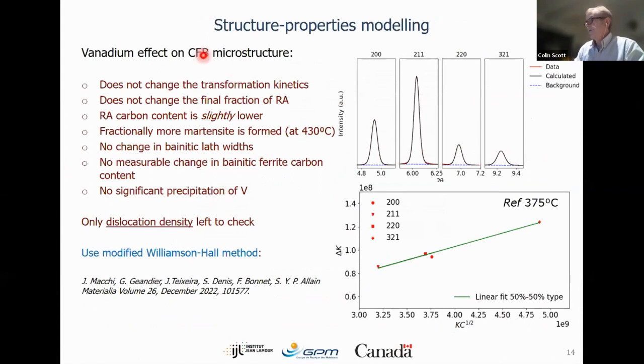So, okay, why does vanadium make these steels stronger? Well, we know it doesn't change the transformation kinetics. It doesn't change the final fraction of retained austenite. There's a slight difference in the retained austenite final carbon content, a fractional difference in the amount of martensite that's formed at higher temperatures, but not really at lower temperatures. No change in the bainite lath widths, no measurable change in bainitic ferrite carbon content, and no significant precipitation of vanadium. So there's only really one thing left, and that's the dislocation density to check.